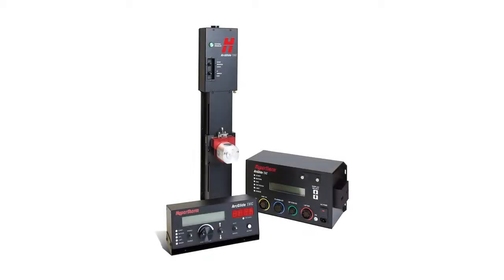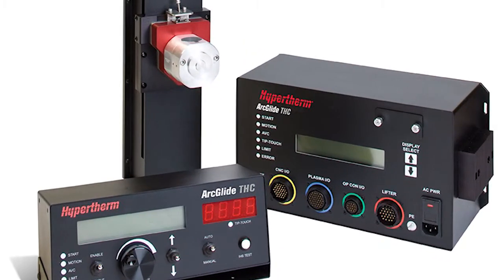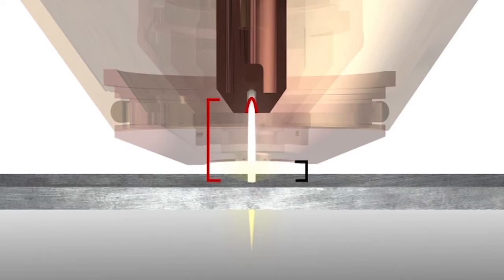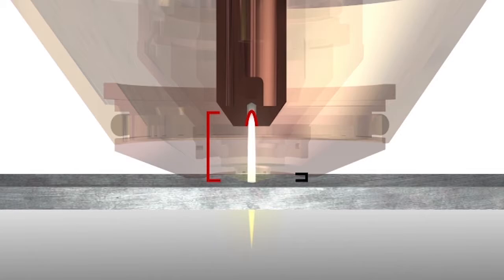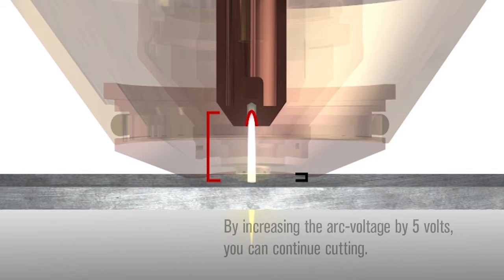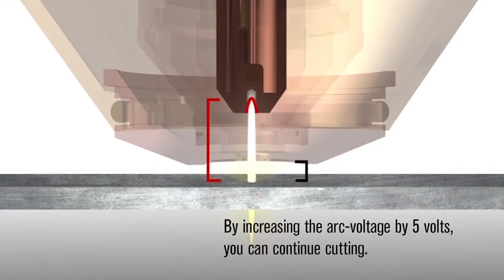If your system has a torch height controller that uses arc voltage to maintain the torch to work distance, the arc voltage must be changed to achieve maximum life and cut quality from a Silverplus electrode. As a silver electrode wears, the set arc voltage will cause the torch to move closer to the plate. When this happens, the system is no longer cutting in the optimal part of the plasma arc, and you'll begin to see greater angularity in your cuts. By increasing the arc voltage by 5 volts, you can continue cutting with the same silver electrode and attain acceptable cut quality.